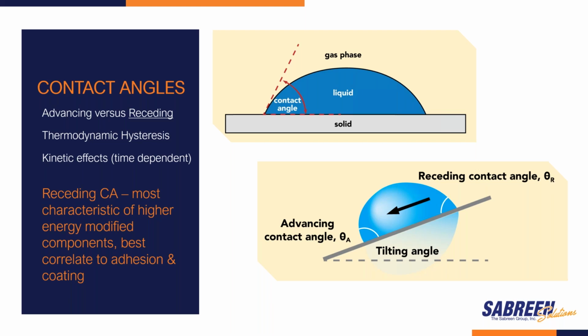Well, we all know that something static in nature is unusual, and that just like taking physics classes in college and high school, everything is based upon theoretical. We're doing this in a vacuum, or we're doing that in a vacuum. So it's really more important to look at what happens to a contact angle or a fluid in the real world. And this is where thermodynamic, hysteresis, and kinetic effects become important. Well, we want to break out into two vectors. The advancing contact angle is most sensitive to the low energy or unmodified components of the substrate surface, while the receding angle is more sensitive to the high energy oxidized groups introduced by the surface pretreatments.